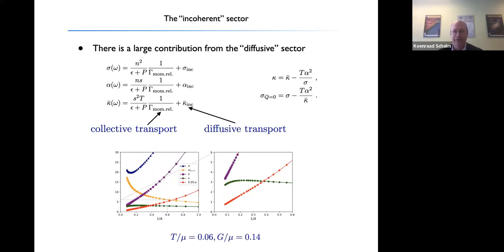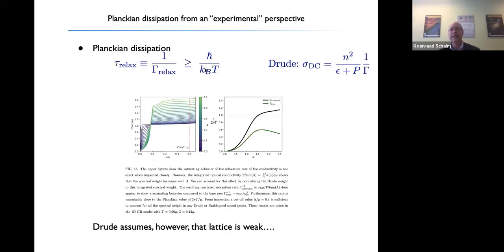Even though all these indications are that there is no such collective term, if you would naively try to extract a relaxation rate in this system for very, very large A, you find something rather interesting. You find that the relaxation rate in units of 2 pi T starts to saturate near 1. You have to do it a little bit carefully, because as you increase A, there's a transfer of spectral weight. If you compensate for that, that's this compensated form, you really see that this starts to saturate at 1. And gamma in units of 2 pi T equal to 1 is a very special value that is very well known in the literature.